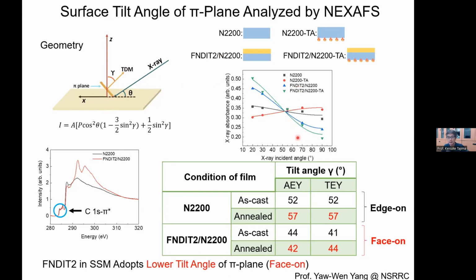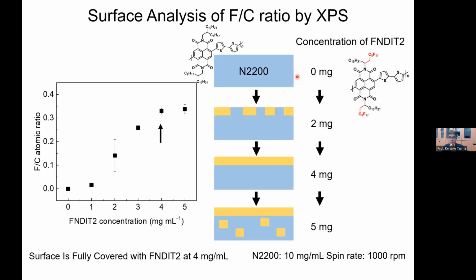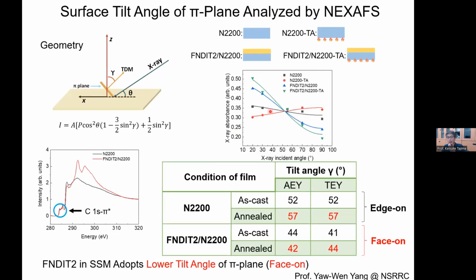And you can see that the N2200, this NDI polymer here, tends to have an edge-on orientation after thermal annealing. You can tell by this curve, the angle dependence is a positive dependence on the incident angle, right? So it's not perfectly edge-on. It's close to the magic angle, but still it has a tendency like this.